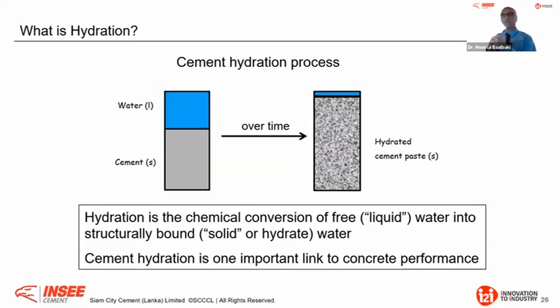But you have what you call the gel pores, and those pores will have part of the water that is chemically, structurally bound. Like when you talk about calcium silicate hydrate, calcium aluminate hydrate, calcium hydroxide, you have water that is chemically bound, okay, these are the gel pores. But you have capillary pores, where the water is not chemically bound, it is only physically bound. Therefore, in some hygrometric conditions, in terms of relative humidity or temperature, we can lose this water, and this is why you have what we call volumetric change, and this implies shrinkage.